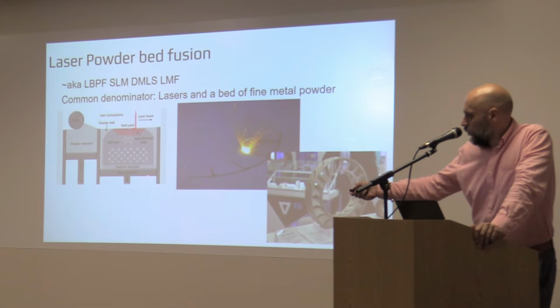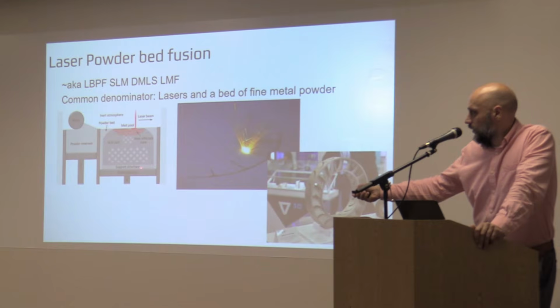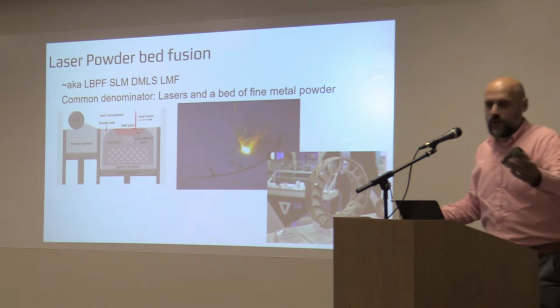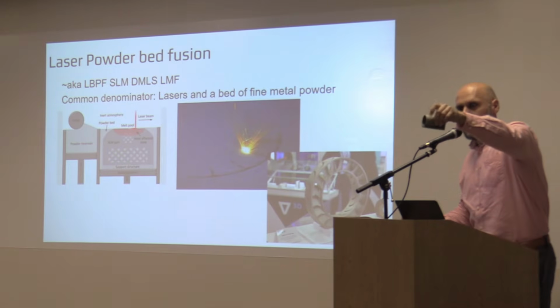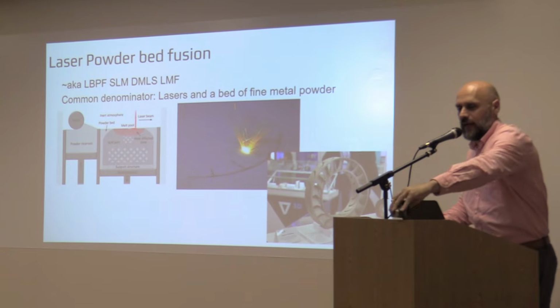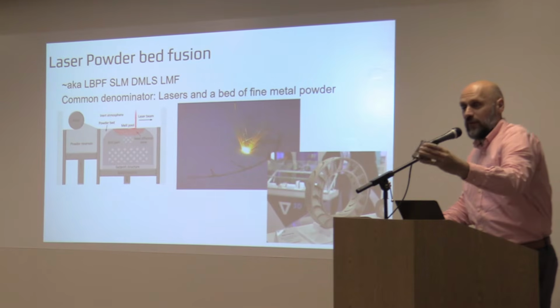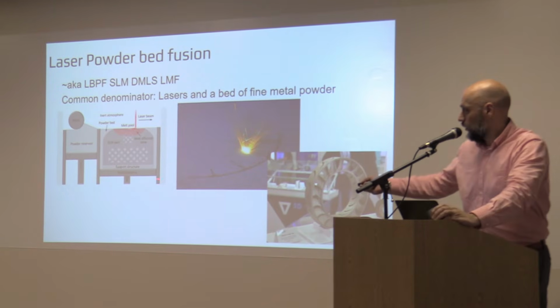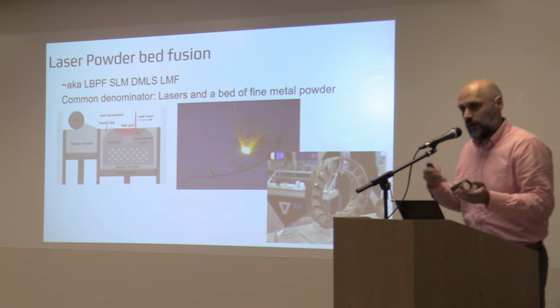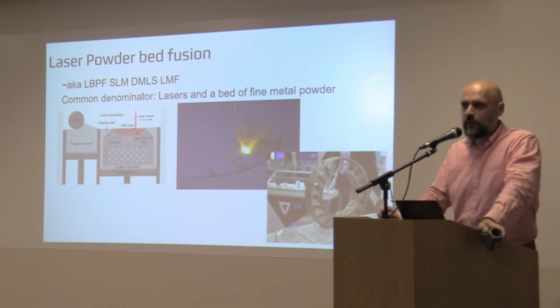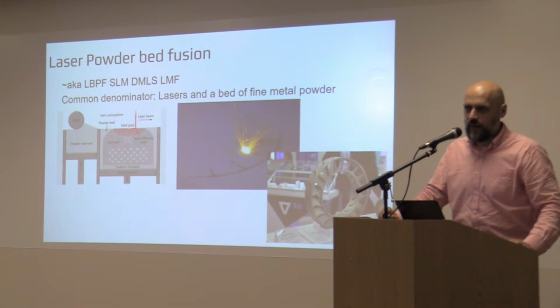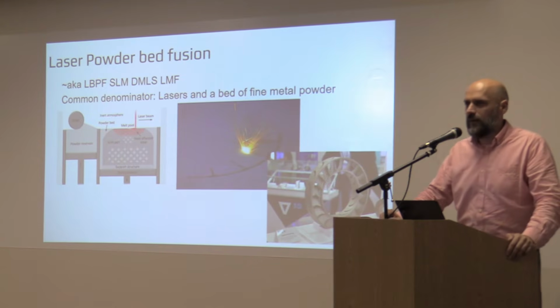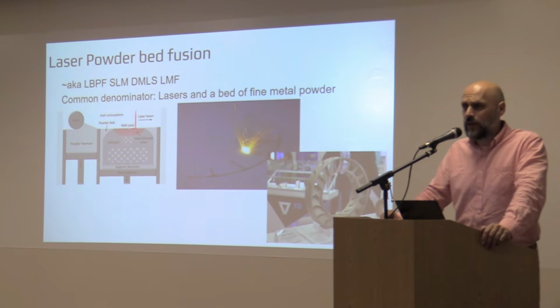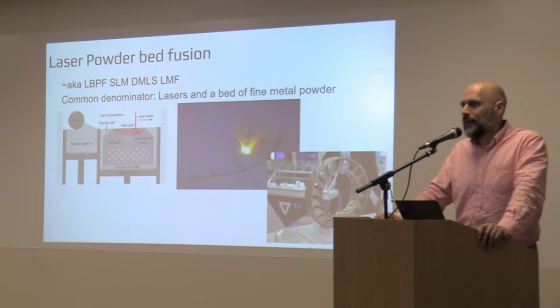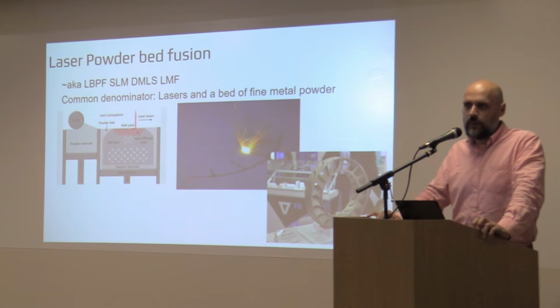So this plate here is bolted down to the main base, and it's a very thick piece of stainless steel. And we see here the support structure. I'll show you more pictures later, but this is an example of support structure. So I want to make this pipe here. I have to somehow have it sit firm on my build plate. Now, if I don't pay attention and I put too much metal, I can cause this to warp because of all the stresses, and I'll explain the mechanism, and it will actually shear the bolts out. And it may destroy the machine, because of all the system that goes back and forth here. Back then it wasn't very smart. There were no cameras, there was no AI to tell you, hey, this is abnormal. The approach we had back then was very basic and logical.